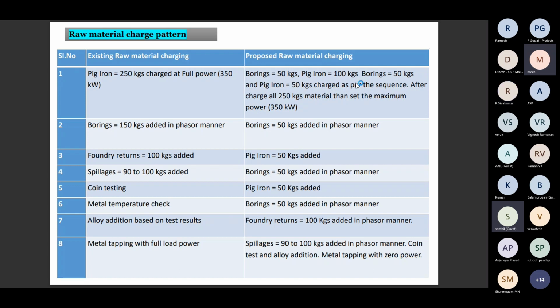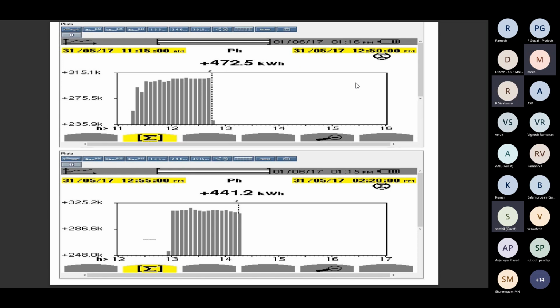Next. So in the existing pattern, this graph is from the power quality analyzer we have. There are energy and power quality measurement instruments we have through our project. So I studied the existing practices. For one melt, it takes around 472.5 kilowatt hours for melting almost 550 to 580 kgs of raw material. Molten metal was taken as 570 to 580 kgs at the 350 kilowatt furnace. For one batch, it consumes nearly 472.5.